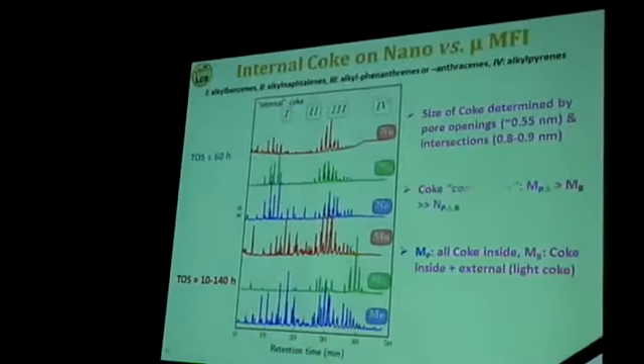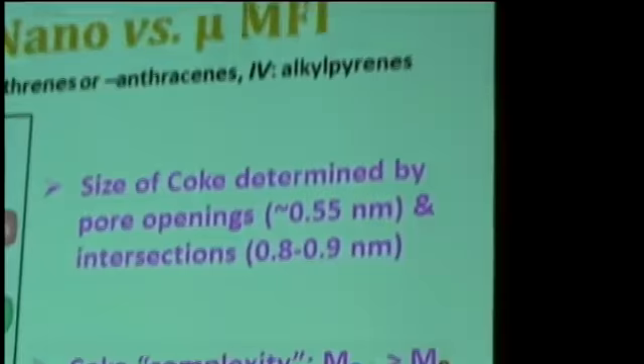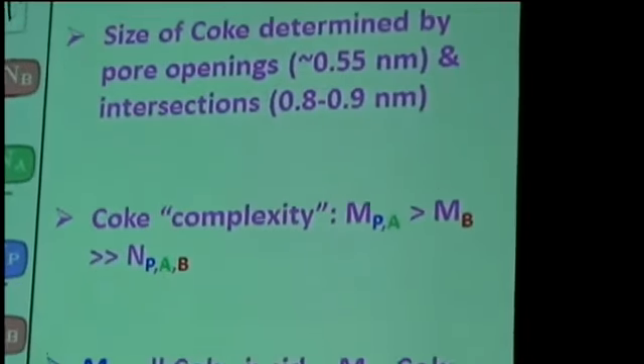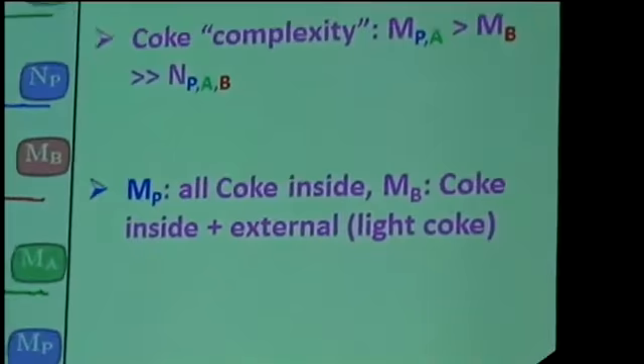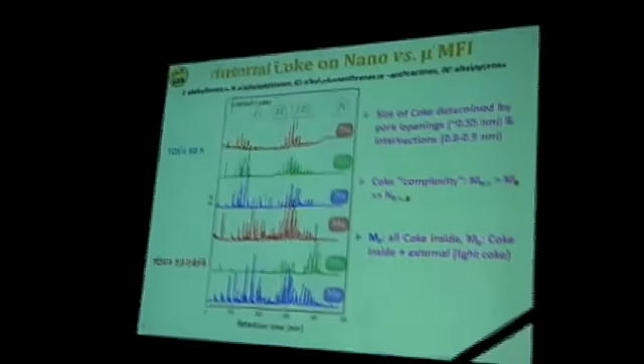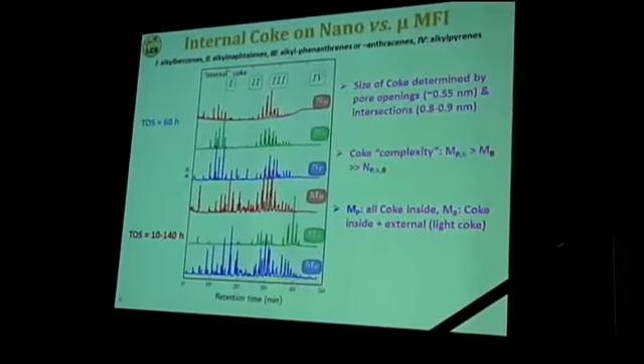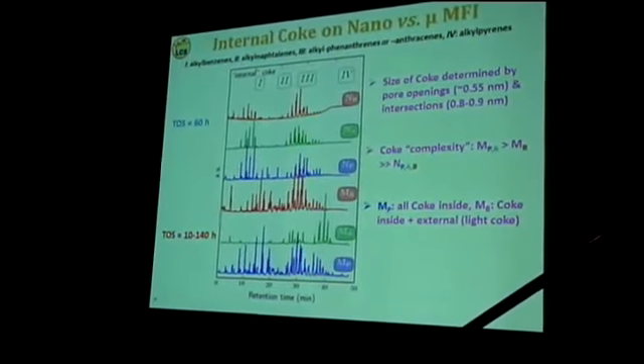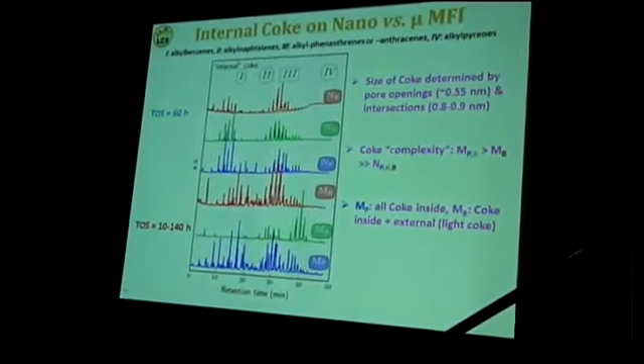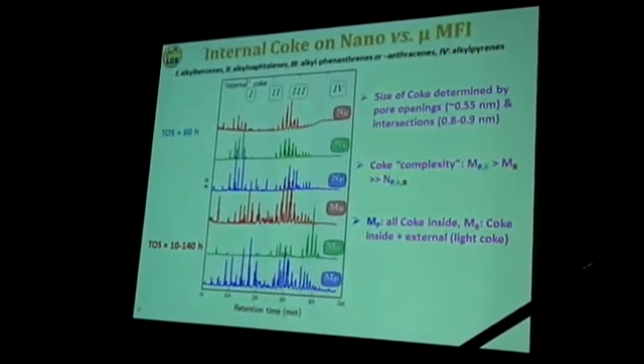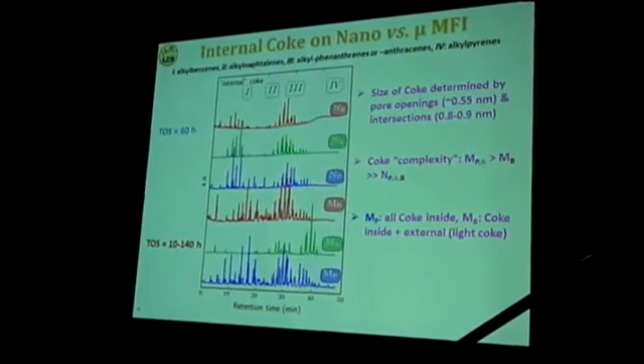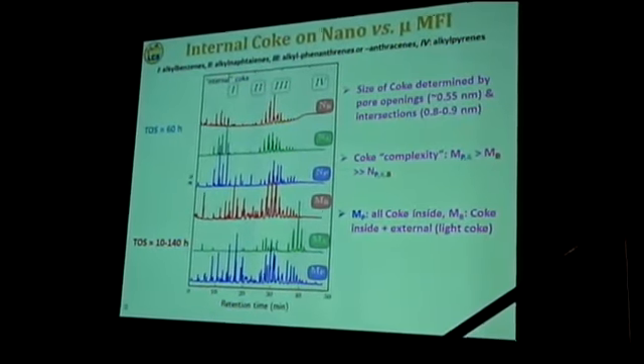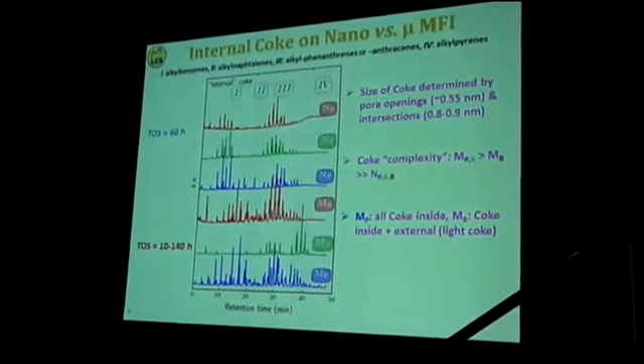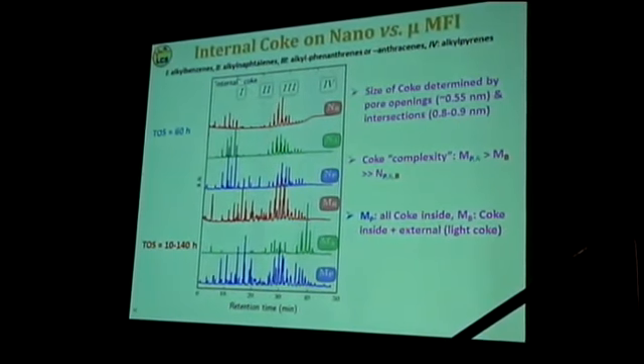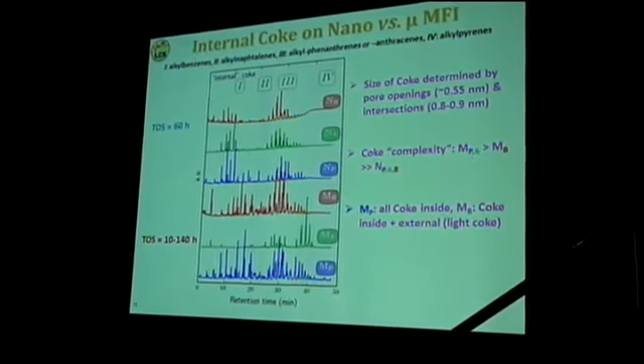And again, what is very interesting, if you look at the size of the biggest molecule that we detected by GCMS, they are basically of the size of the intersection of ZSM5. So basically, coke is a shape-selective reaction. It ends when the zeolite says this is the end of the game. I will not go into the details, but you can see that the complexity of the coke, the distribution of the different products, is more complex for the parent micron-size zeolite, and then the material where few macropores have been added.